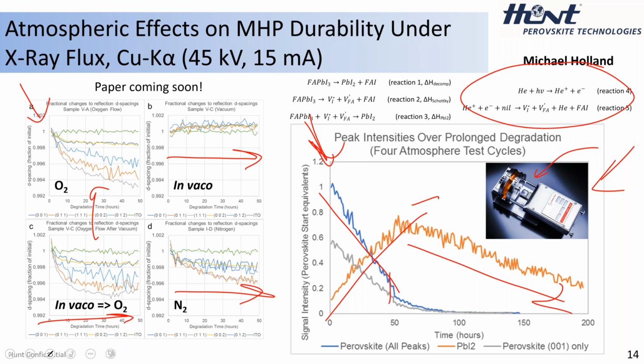So again, we have this kind of cyclic system here that is resulting in vacancies, and these vacancies at some point will decompose the material. And so you can see here to the left of that 3 other reactions where you have kind of standard decomposition in reaction 1, so FAPbI3 decomposing into lead iodide and FAI. This is the opposite of how it's formed. But if you form Schottky defects in some way, i.e. what's to the right here, this is a different way for it to decompose. And then you have more pure FAPbI3 without vacancies react with this material with the vacancies. So the vacancies cause an overall decomposition to lead iodide. And that's another way for us to get to that final decomposed product. So loss of FAI and the creation of lead iodide. So I did mention the creation of lead 0 also. I'll come back to that with a different data set.